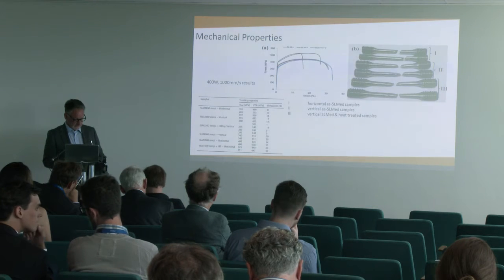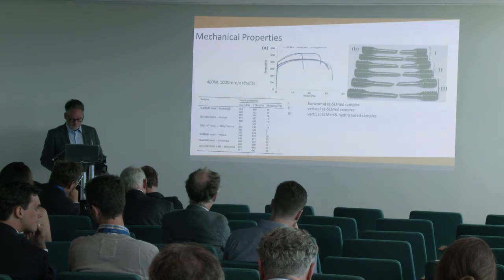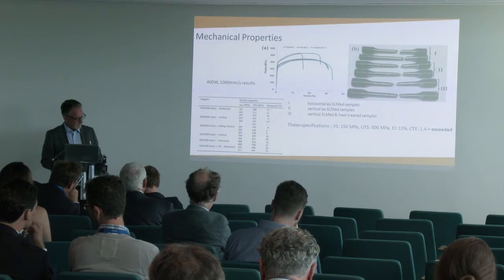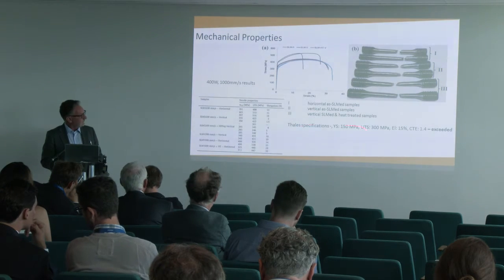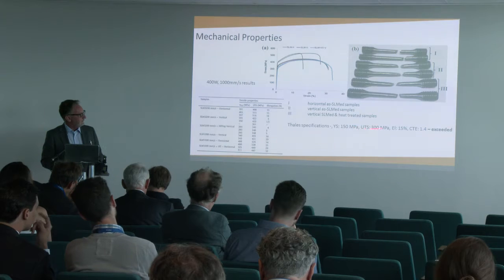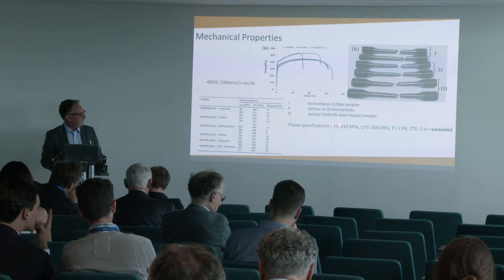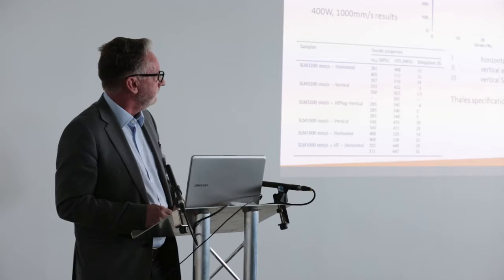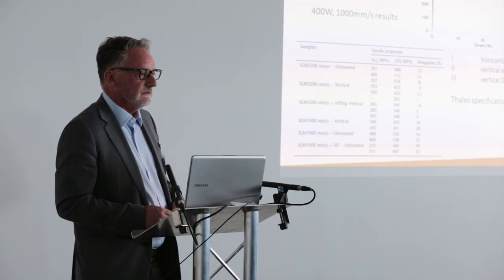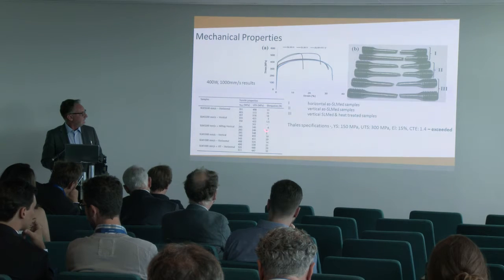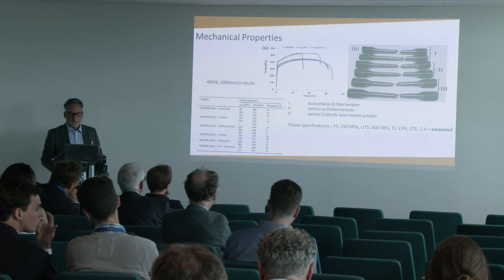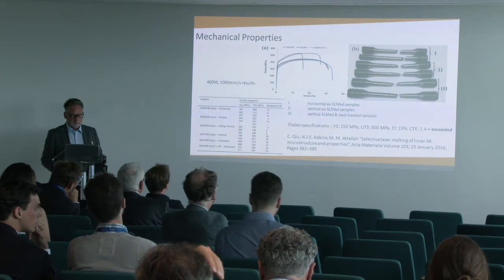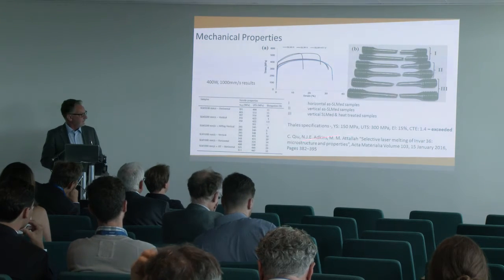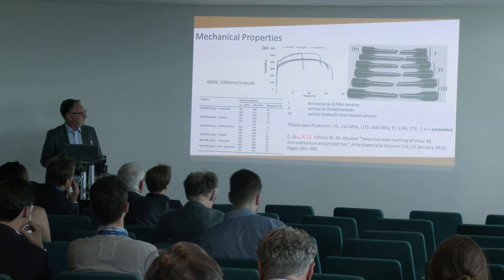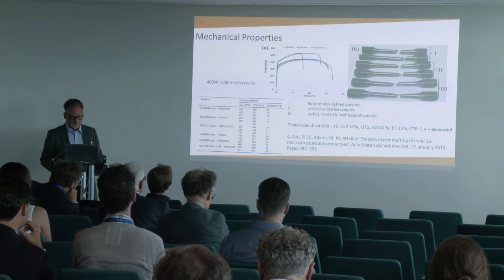We measured the mechanical properties. There are some targets which were set by Thales here, down at the bottom, and the material exceeded those by a long way for the yield strength and UTS, just about for the elongation and certainly for the CTE. So they were exceeded. So the processing of the material seems quite suited to this. And there was a publication which you may want to look at, which is also in your brochure, which we wrote as a paper in Acta Materialia.